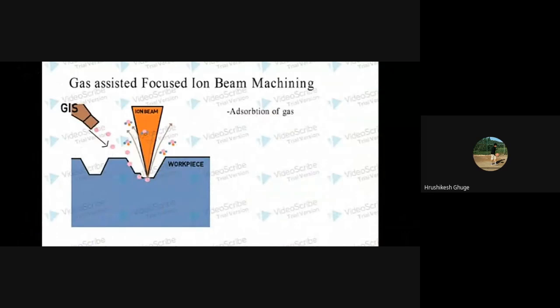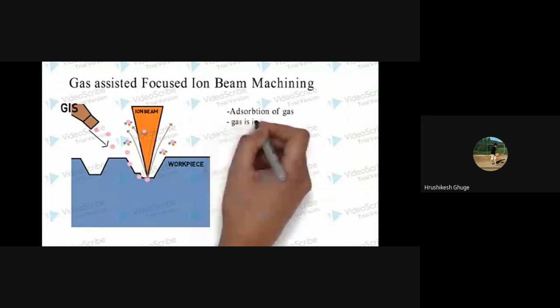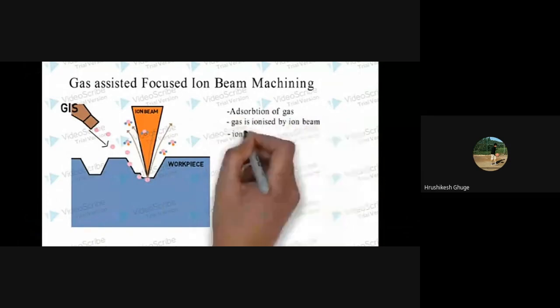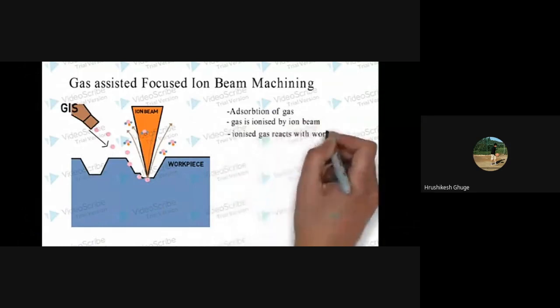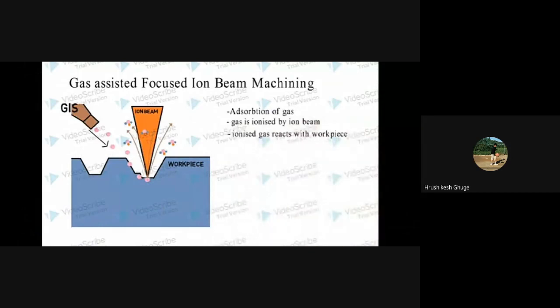When the ion impinges on the surface, the adsorbed gas atoms ionize and they chemically react with the substrate surface, which helps the milling process. This compound formed is most of the time volatile, so it is removed from the workpiece. So reactive gas deposits on the surface, reacts with the ion and obviously the workpiece, and is removed as a volatile material. This will solve the problem of redeposition, thereby increasing the accuracy of the machined feature and enhances the material removal rate.